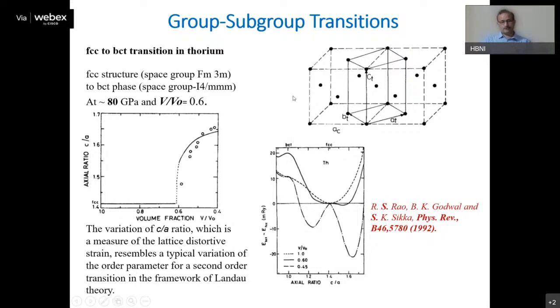Now let us take an example of the subgroup kind of phase transition. I take a classic example of the FCC to BCT transition in thorium. In any FCC structure, you can make a tetragonal unit cell by joining these face center atoms like this. As long as the system is in the FCC phase, if you compare the c by a ratio, it will be 1.41, basically square root of 2. So as soon as the value is square root of 2, it is in the FCC phase.